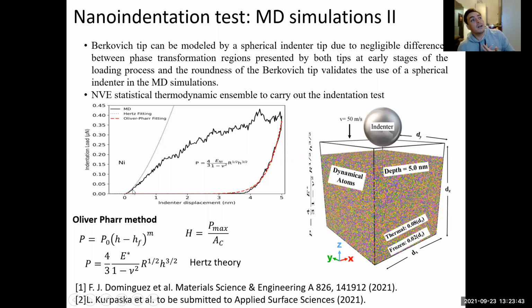And this part here is the so-called elastic part of the loading process. Why are we calling it the elastic part? Because it's only the interaction between the sphere and this plane. According to the Hertz theory, we can fit this part with this expression. It's only the interaction of the sphere with the plane, and it fits very well. Also in experiments, when you do a spherical nanoindentation test with a spherical tip, it also follows the Hertz theory.